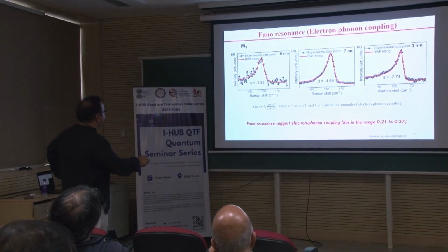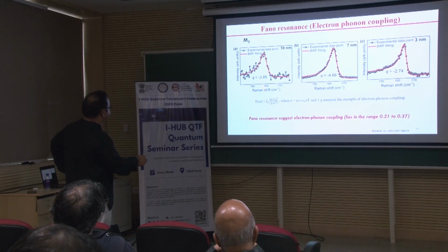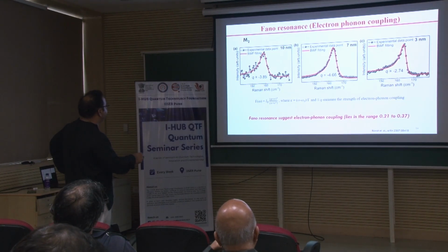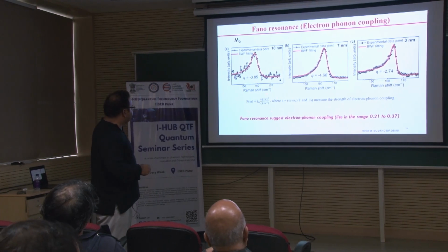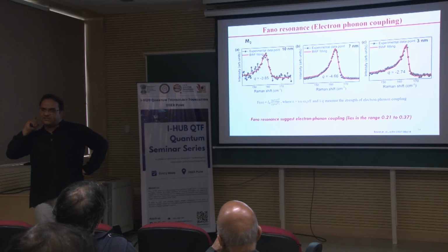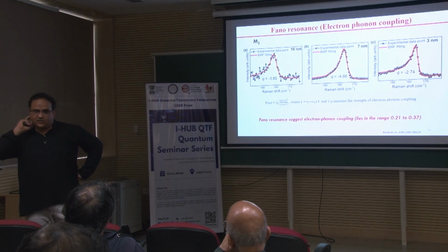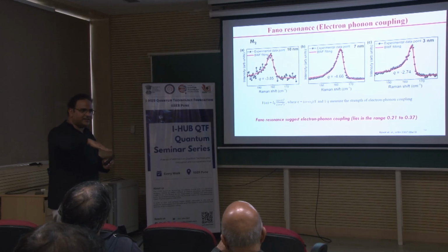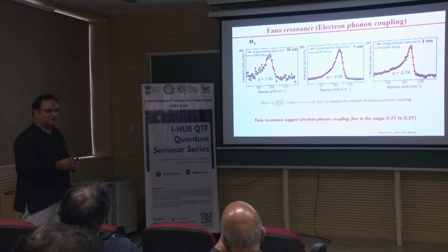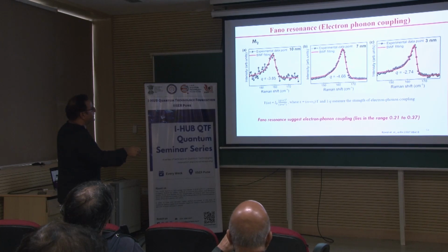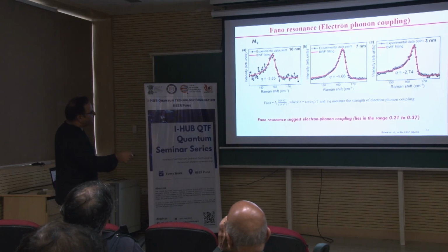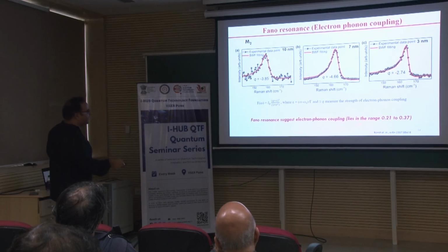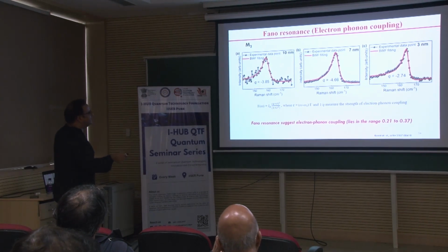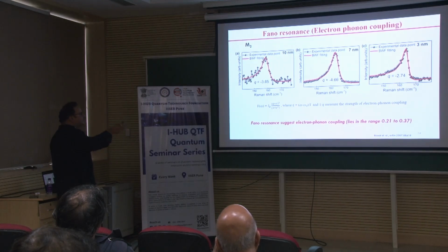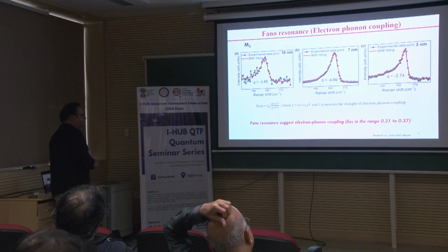And this is the Raman mode for one of the modes, almost like 158 or something. We fitted with the Fano line shape analysis, and we found that the Fano line shape actually tells you how much is the involvement of the electron phonon coupling, and the slope of the Fano line can tell you whether it is an N type or P type material as well. So, we found out that there is a clear cut involvement of the electron phonon coupling below 16 nanometer or 10 nanometer, which is enhanced in the lower thickness flakes.